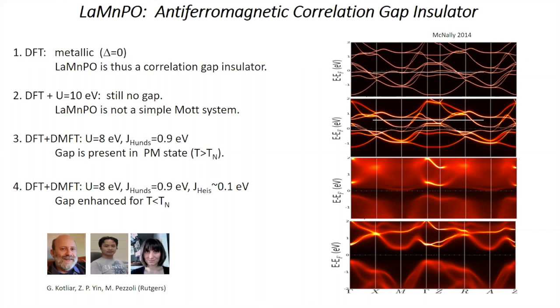The second panel down takes the DFT and adds a quite large Coulomb interaction of 10 eV. And you can see that that did not materially change the situation. Again, there's no gap. And so that suggests to us that this material is not a simple Mott system. The first indication of a gap happens when we add a Hund's interaction of about 0.9 eV, and there is no magnetic order present in this state. And you can see that for the first time we see a small gap.